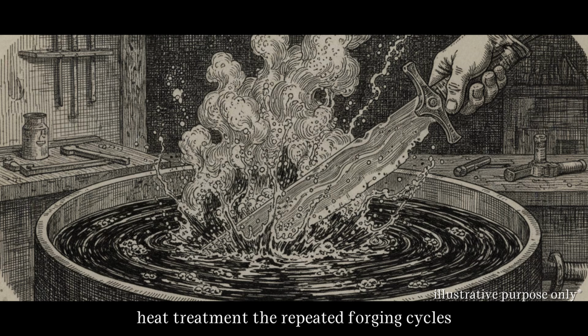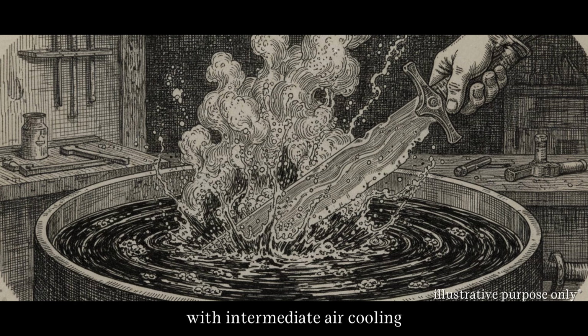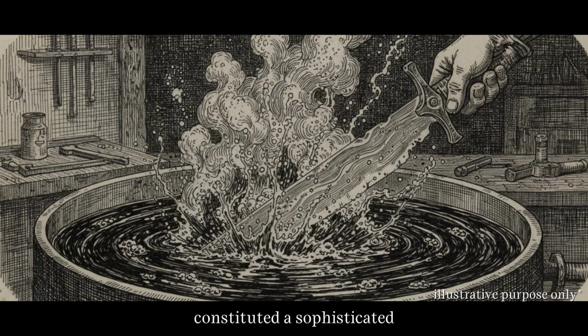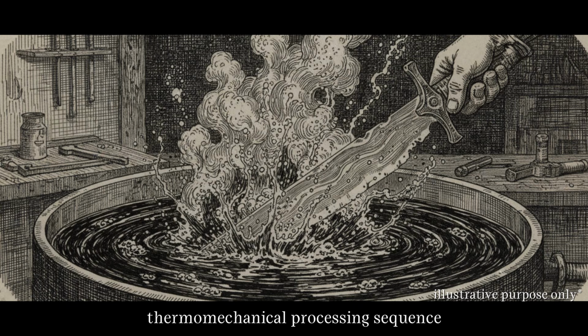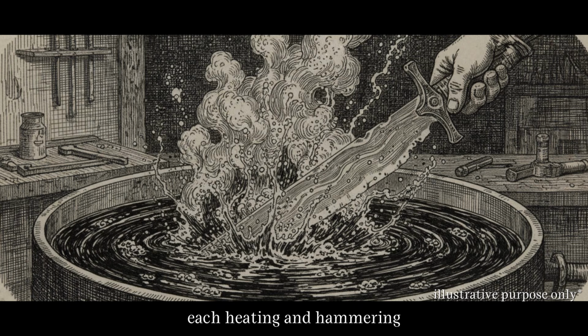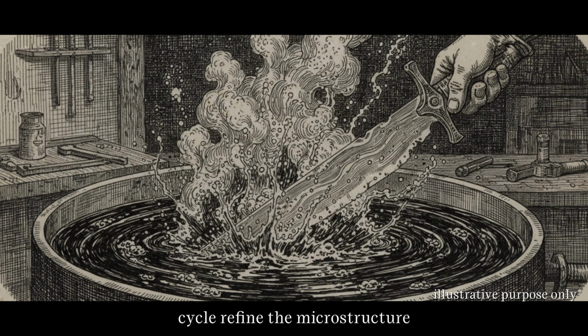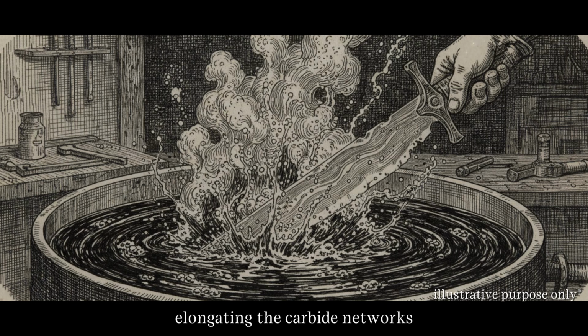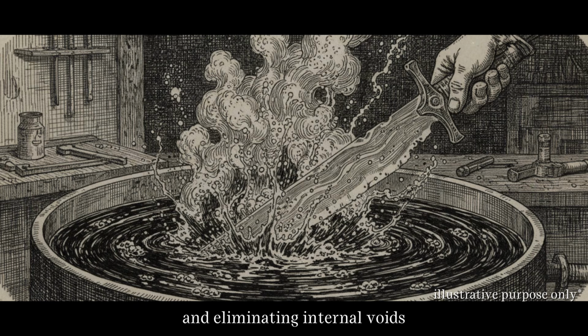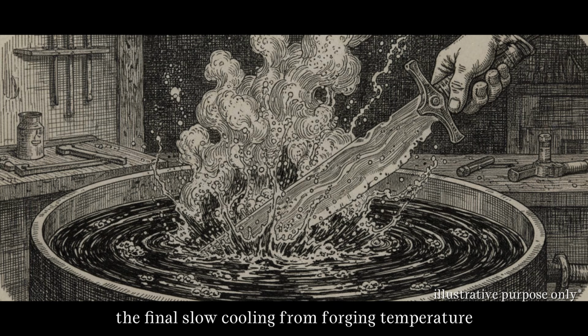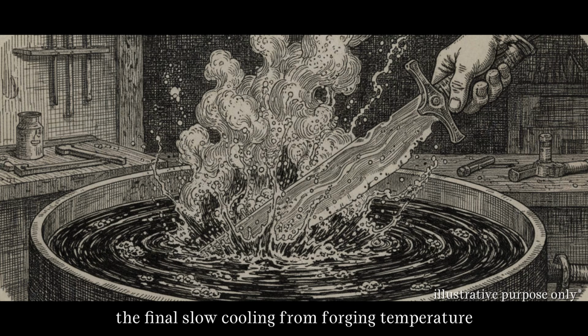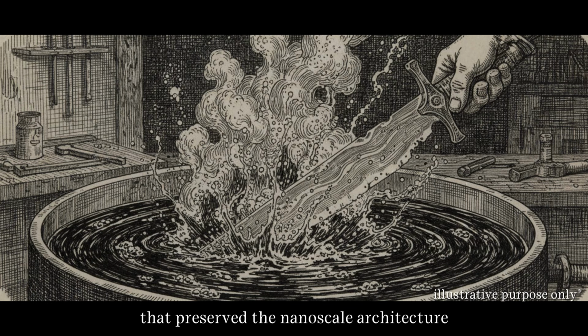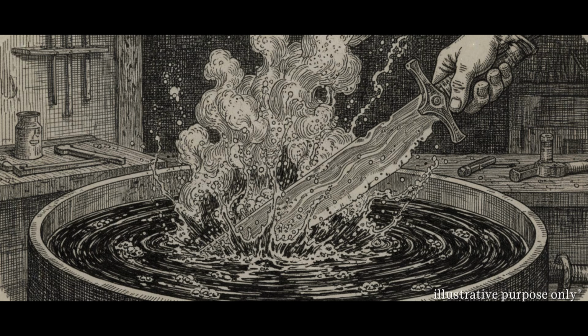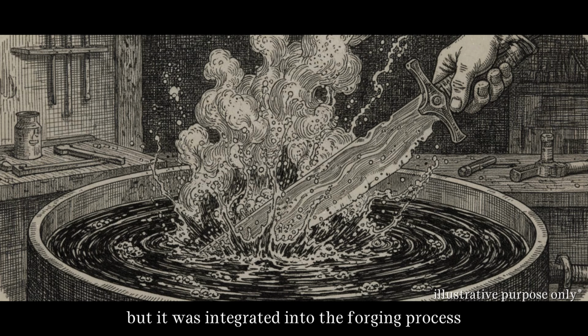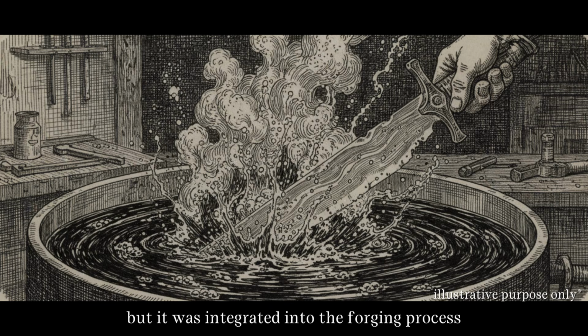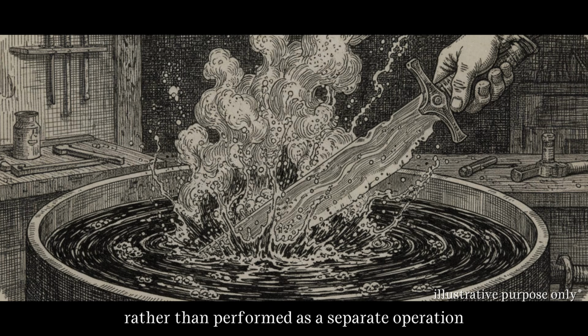The repeated forging cycles with intermediate air cooling constituted a sophisticated thermomechanical processing sequence. Each heating and hammering cycle refined the microstructure, elongating the carbide networks and eliminating internal voids. The final slow cooling from forging temperature was the crucial step that preserved the nanoscale architecture. This was heat treatment, but it was integrated into the forging process rather than performed as a separate operation.